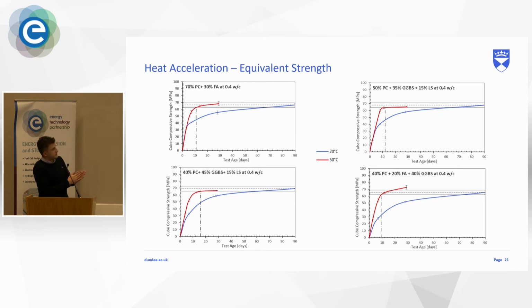And you can easily see that at 50 degrees, the strength develops much more rapidly than when cured at 20 degrees. And if you look at the dotted line, the 90-day strength is now achieved within the first 12 days of 50-degree curing. So as I said before, there's a good chance that if we match the strength performance, the durability will be unchanged.